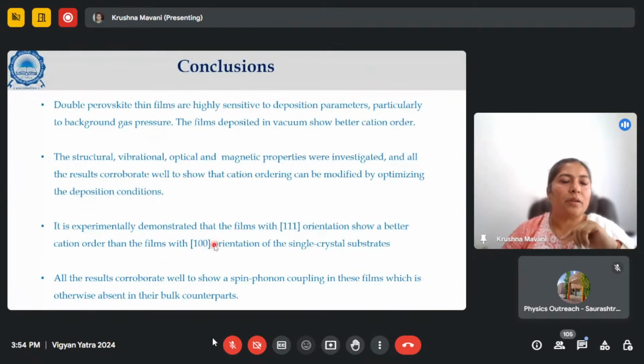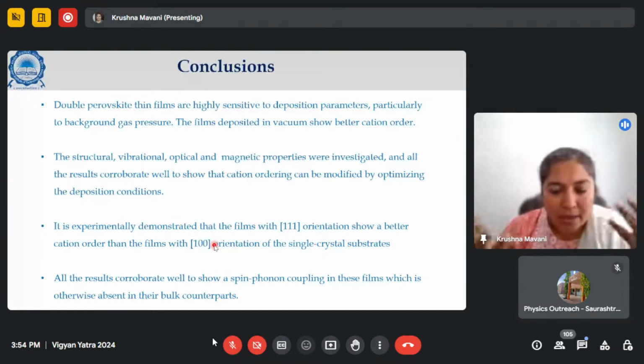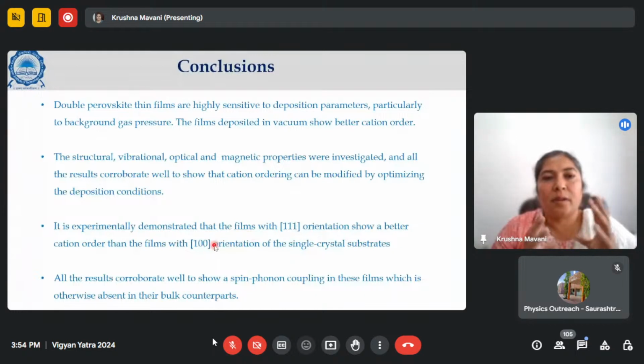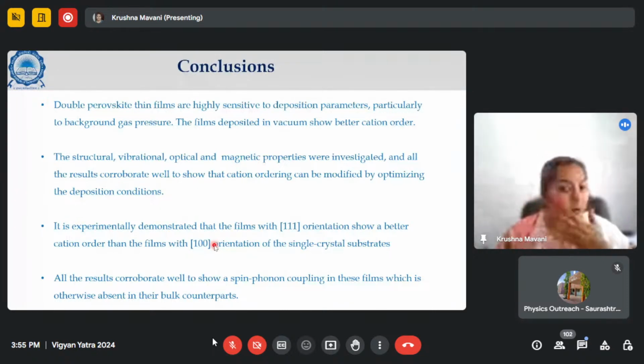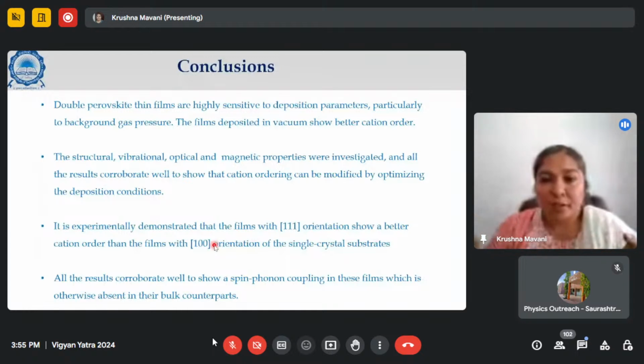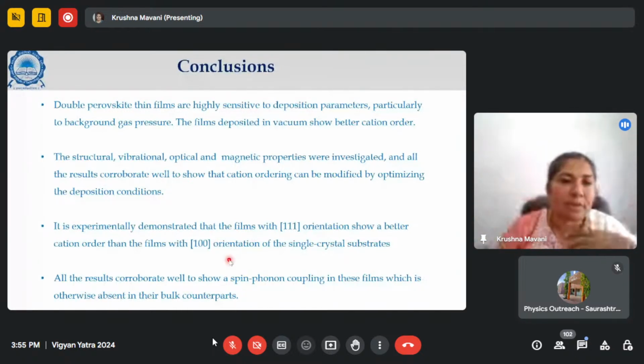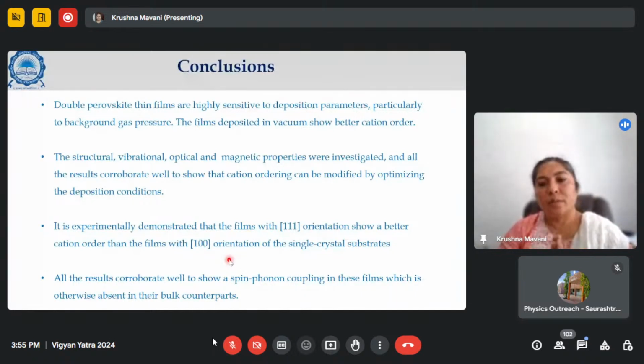Okay. So to conclude, this is the conclusion mainly on our results. These double perovskite thin films are highly sensitive to deposition parameters, particularly the background gas pressure. We have successfully produced nice films in vacuum condition. Then we have done various experiments and modified as per the different deposition conditions and substrate orientation. And we have experimentally demonstrated that 111 orientation is the best to get the cation order. And all our results corroborate very well to show that there is a spin phonon coupling in these thin films, which is absent in their bulk counterparts.